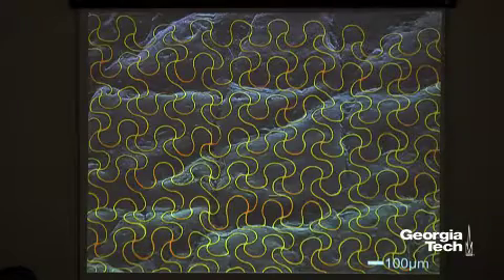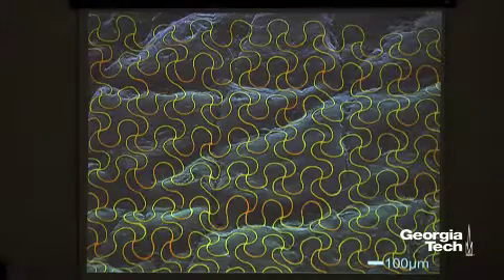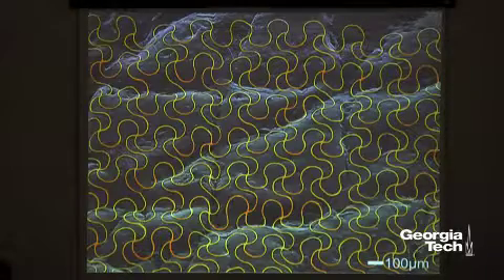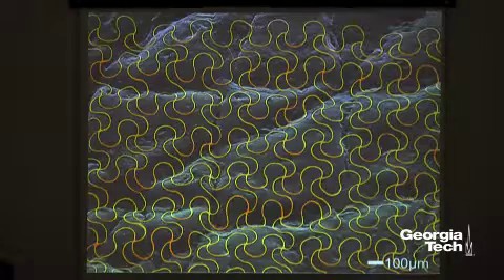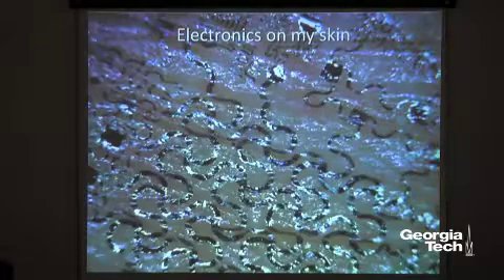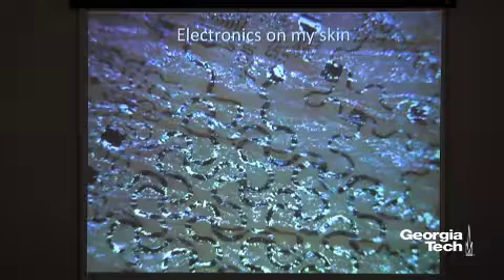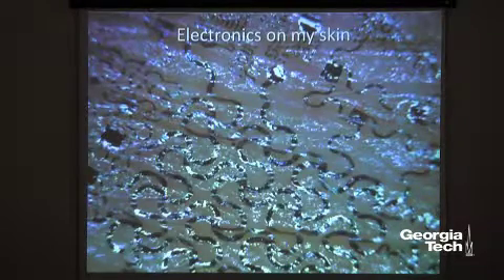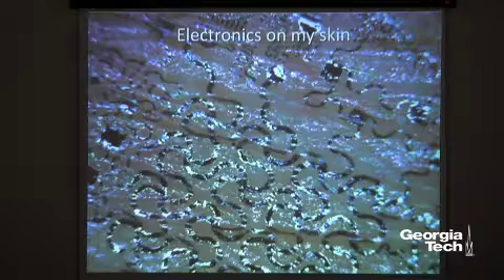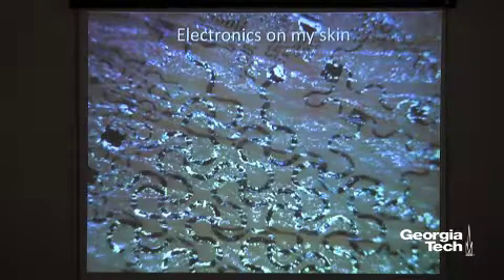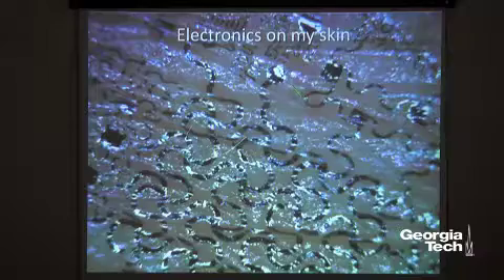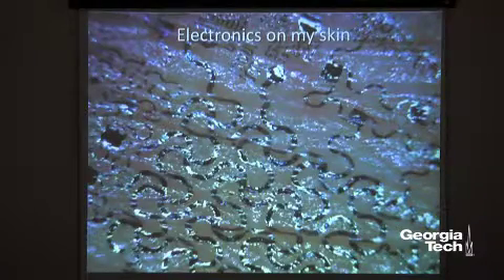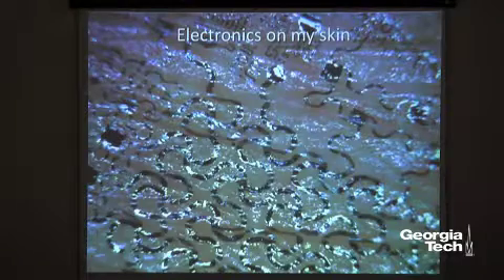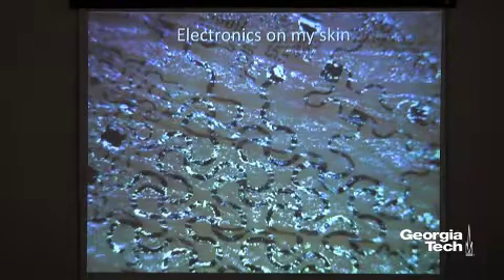Okay? So by using this ultra thin electrode, you don't need to use this conductive gel, so that you have a completely dry configuration for measuring biopotentials, like the electrocardiogram that I mentioned earlier. All right? And that's actually my skin with a microscope, right? So even though it looks dark here, based on microscope, it is very clean and white. And as you see, my skin has these wavy patterns, right? And that's the printed electrode over the skin. So it looks very good in terms of this contact.